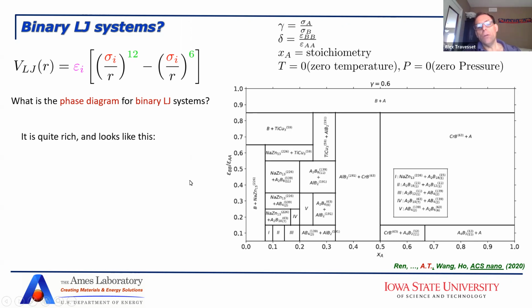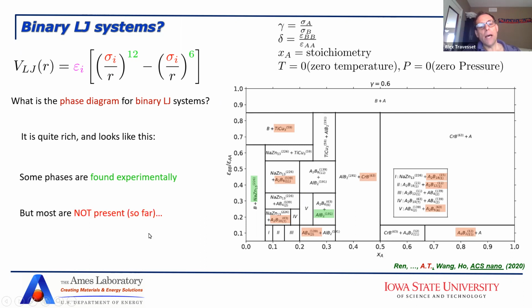On first look, it seems that you have some successes. You have sodium zinc 13, which is something that the experiments have found. You also have aluminum boron 2, which is another thing that the experiments have found. That looks like a good thing. But then you realize that you also predict a whole bunch of other phases that have never been seen in the experiment, those are the phases we predicted for the phase diagram of the binary Lennard-Jones system. Not only that, you are introducing a new parameter, and then you have the job of relating how this parameter relates to the properties of the nanoparticle.